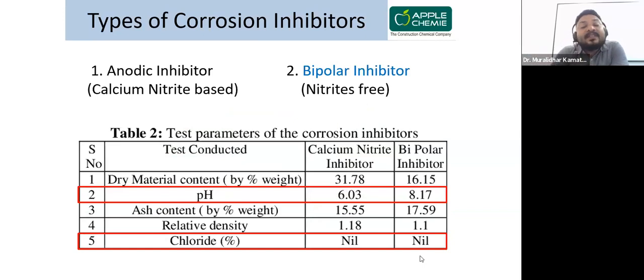Then how can you check the corrosion inhibitor solution, which one it is? If you check the pH, 6.03 for calcium nitrite and 8.17 for bipolar, you can identify your bipolar corrosion inhibitor is nitrite free. And the relative density, and the chloride content in both the cases is nil, but the best way to check is your pH over here.